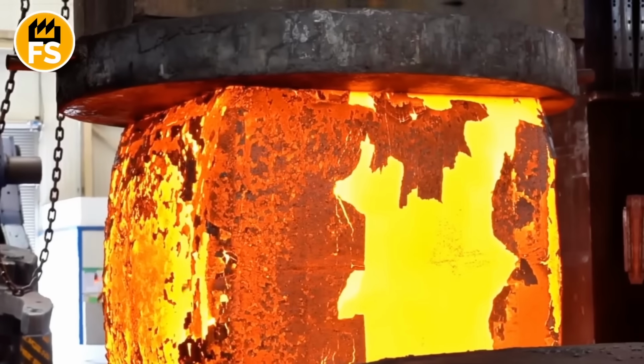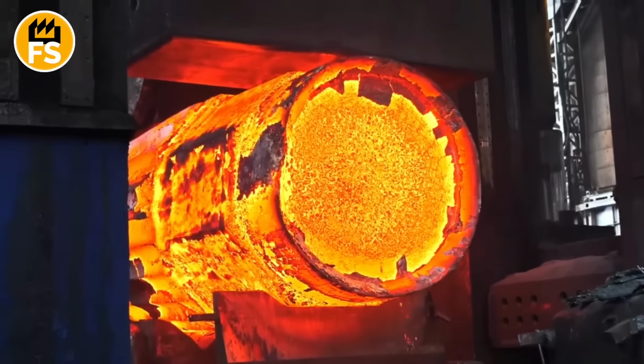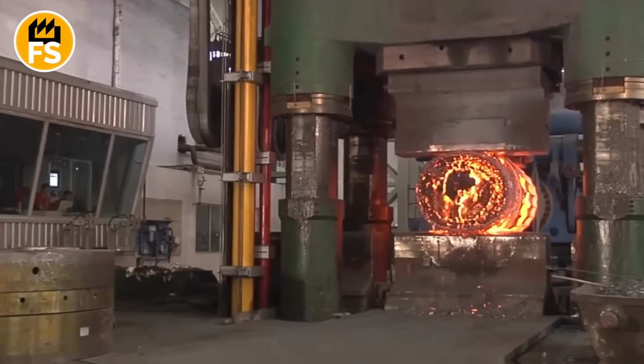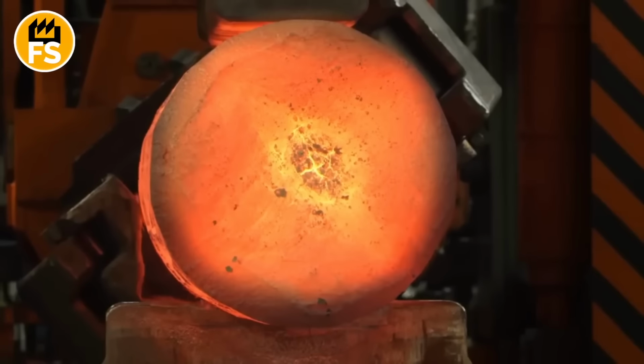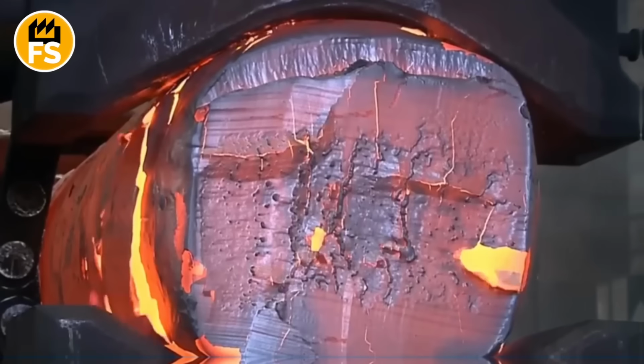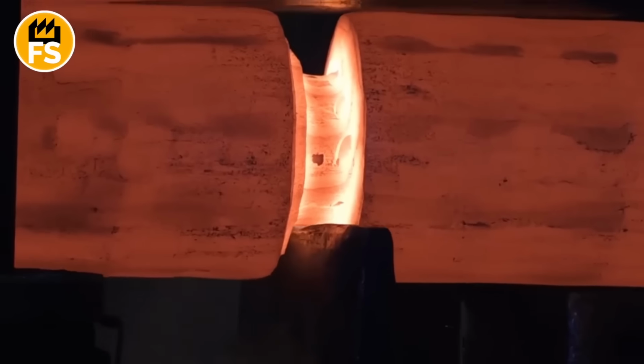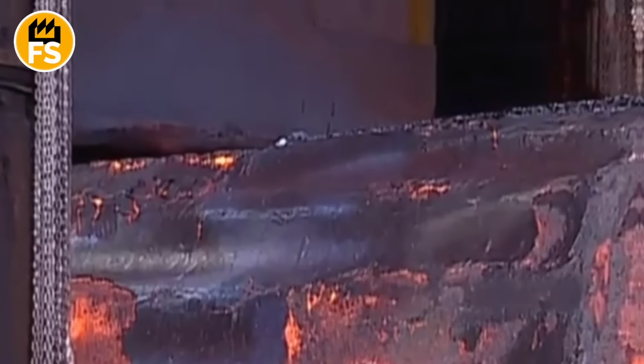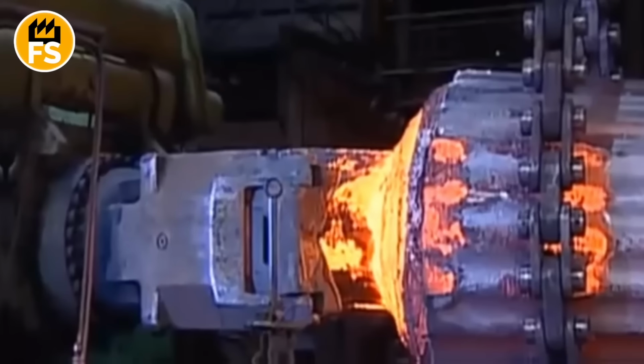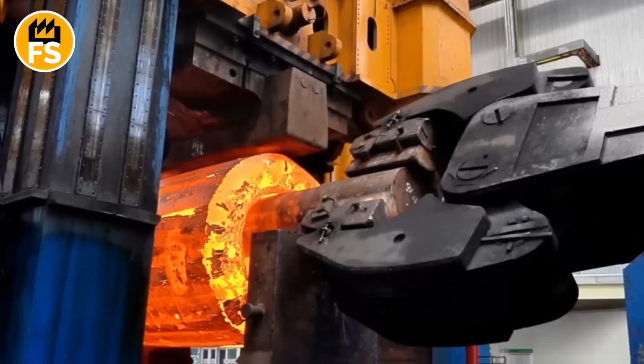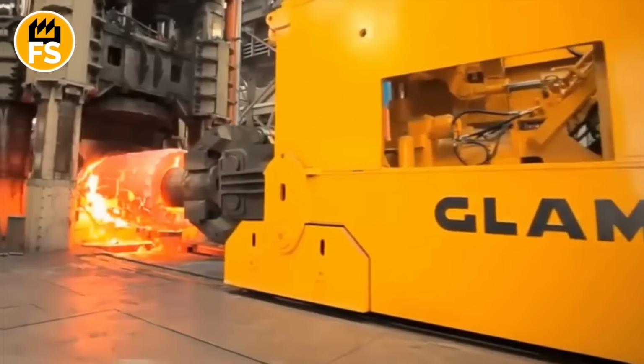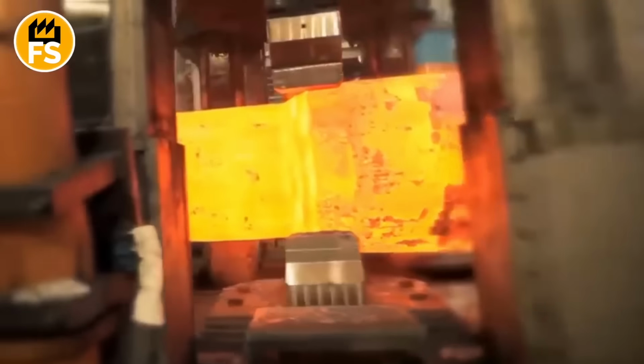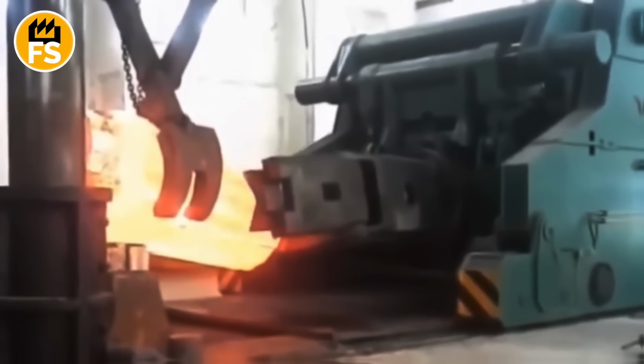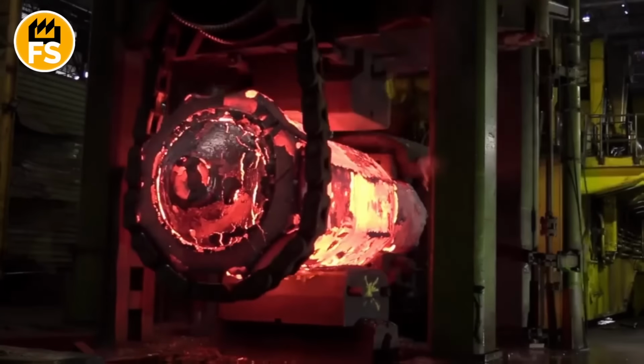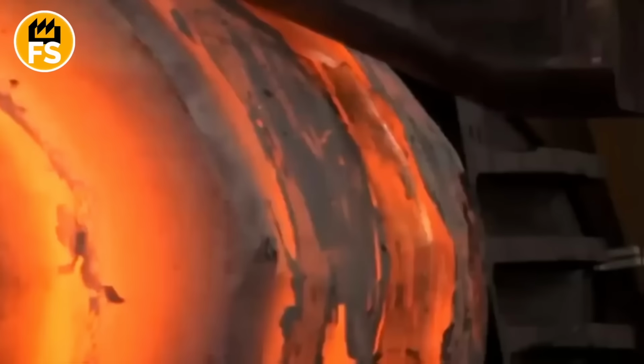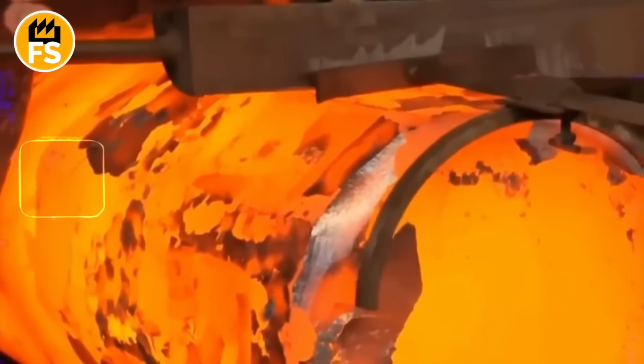Once the heated ingot hits the press, the most spectacular part of the process begins. Giant hydraulic pistons, each the size of a small room, slowly descend with incredible force. The metal, glowing red hot, starts to deform plastically, taking on the desired shape. This isn't a quick strike, like old-fashioned hammers. It's controlled, massive pressure that lasts seconds or even minutes. During the forging of a 200-ton workpiece, it needs to be rotated periodically to ensure even processing from all sides. Special manipulators handle this, enormous mechanical arms that can carefully rotate the white-hot metal giant. These manipulators themselves weigh dozens of tons and are controlled by advanced coordinate systems, ensuring millimeter precision even when working with such colossal masses.